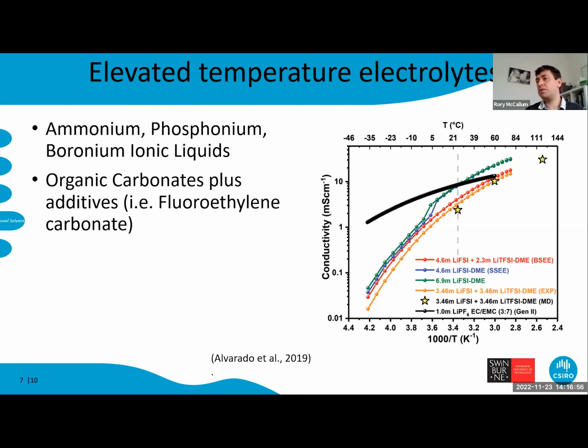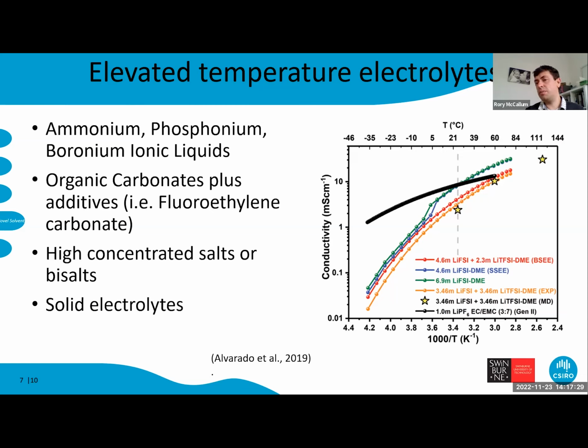If we look at additives, we can look at fluoroethylene carbonate. That's often used as an additive and helps prevent SEI decomposition. And high salt concentration and bisalt systems. So we can think about water in salt electrolytes, or we can use these DME with bisalt systems. And here we can see we can get conductivities actually higher at those higher temperatures than even the standard electrolytes. So, but they're still quite flammable.